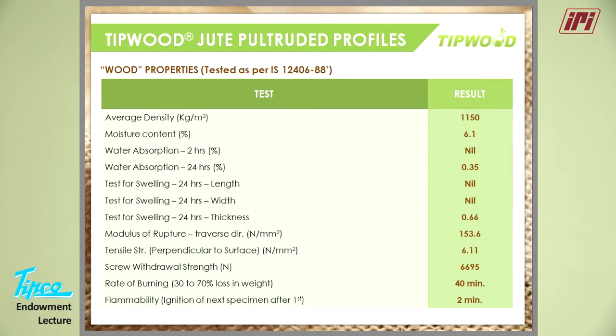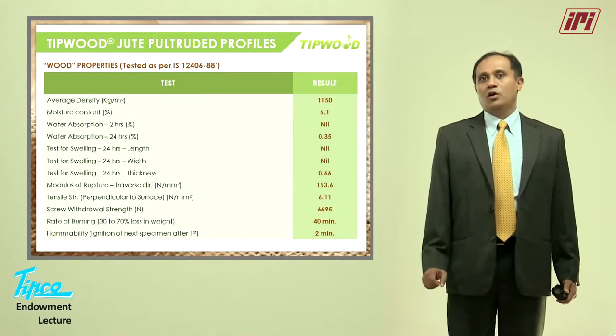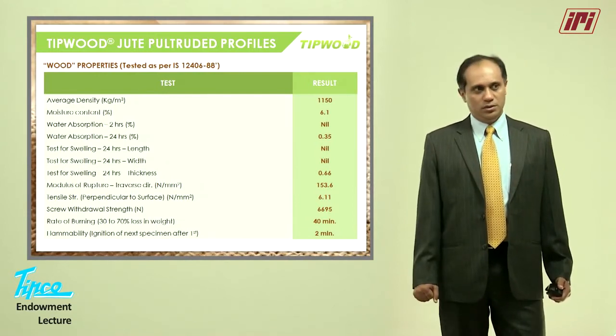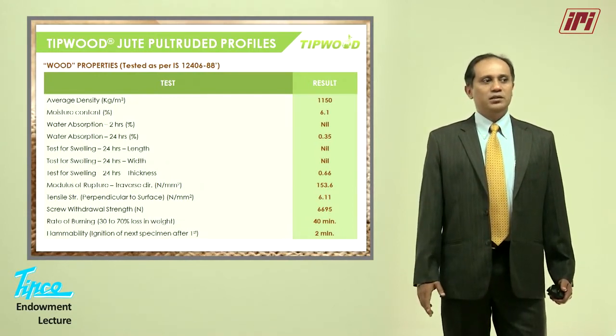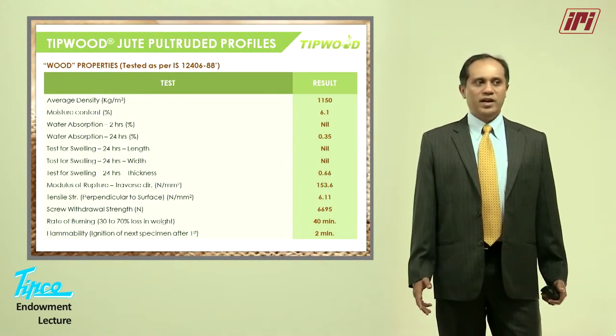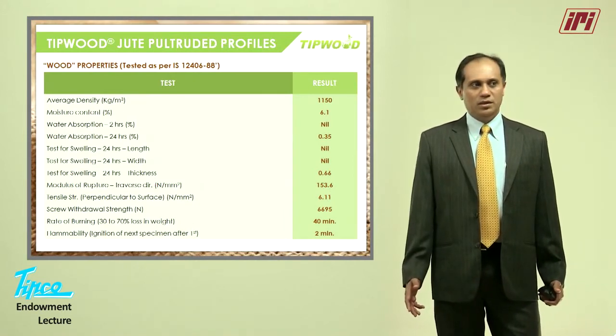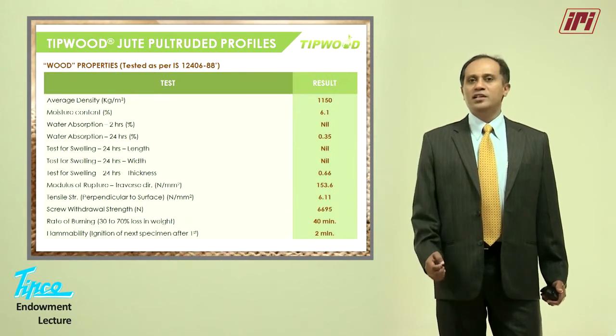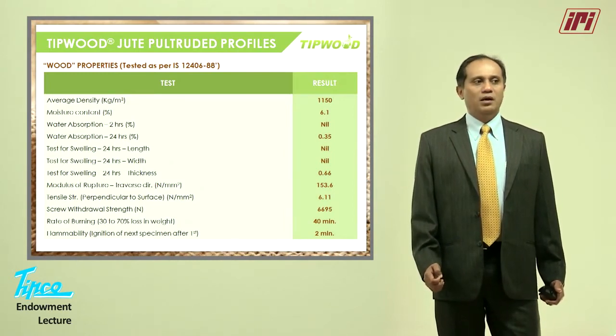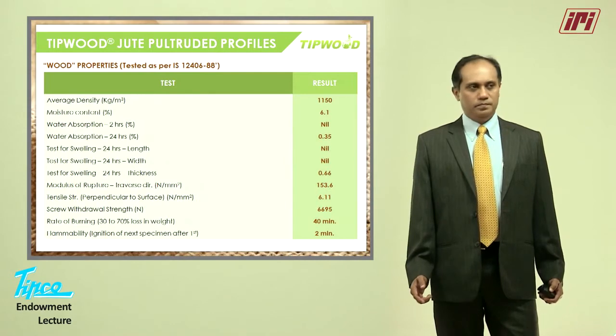We have done tests for modulus of rupture, tensile strength, screw withdrawal strength, very high screw withdrawal strength of almost 7,000 newtons. Rate of burning, 30 to 70% loss in weight in 40 minutes. And flammability, that is ignition of specimen, is around 2 minutes.